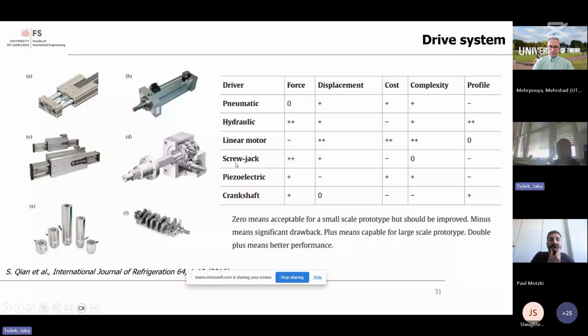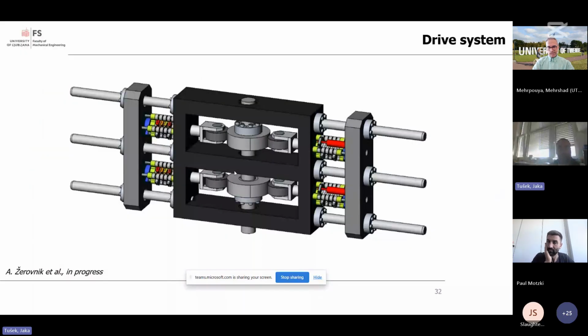From the efficiency point of view, the best choice is probably electromotors, which show efficiency up to or even above 90%. So we have designed an elastocaloric driving system based on a rotary electromotor with a cam disc that loads and unloads four phase-shifted elastocaloric generators with the goal of work recovery. As mentioned by Julie, a precondition for an efficient elastocaloric device is that the energy released during unloading is efficiently used by direct loading of another antagonistic regenerator on the other side of the system.